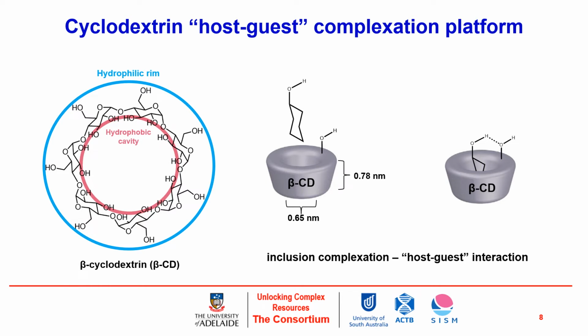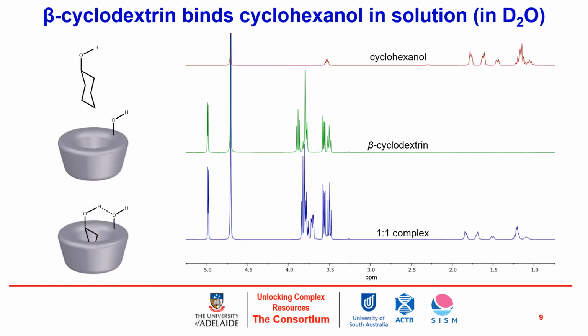And this is the area that we were looking to synthetically modify to be able to produce the materials necessary to validate these in application. On the right-hand side of the slide, I have an illustration of the concept of this inclusion complexation or host-guest chemistry, where cyclohexanol is able to dock within the hoop structure of beta-cyclodextrin and facilitate this interaction, not only through hydrophobic interactions, but potentially hydrogen bonding with peripheral hydroxyl groups from the cyclodextrin.